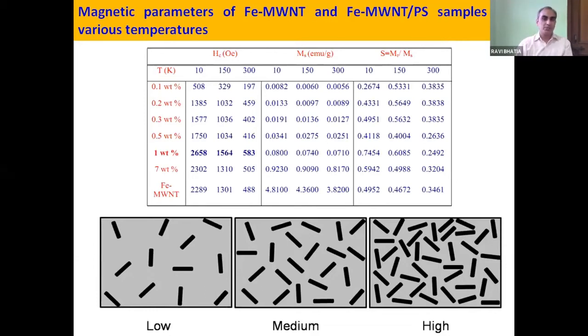So we tried to speculatively provide some answer, because the reviewer always asks what the reason is for this particular behavior. So I will start from high to low or low to high. It's immaterial. Let's start from high. These black elongated particles represent iron nanoparticles, and the other part is polymer or CNT, because CNT alone shows diamagnetic nature, polymer alone shows diamagnetic nature. Only the MH loop appears because of the ferromagnetic iron particle.